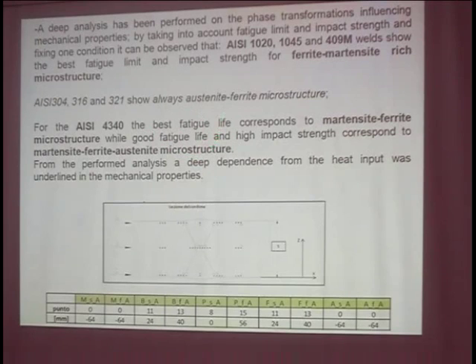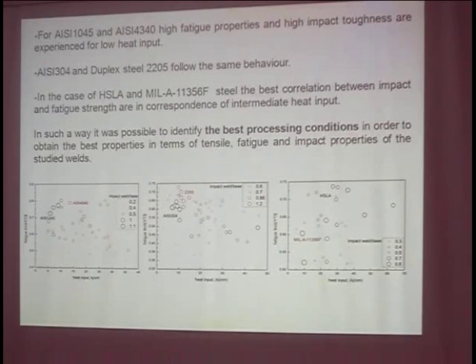So you have to choose if you want just the best fatigue life, not taking into account the impact strength, but if you want good behavior in terms of both fatigue and impact strength, you have to induce a very different microstructure through your processing parameters. And we found finally, because you have to indicate a macro parameter in this evolution, you have to say, okay, I want just this weld through this heat input, and so you fix all the processing parameters during the weld.